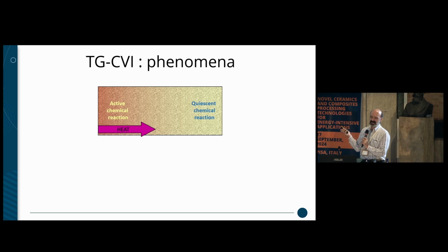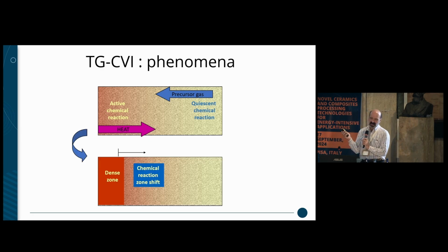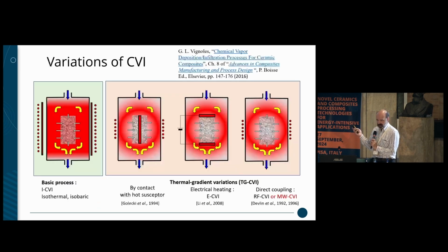And the idea is that, of course, the chemical reaction is active in the hot part. Then the precursor gas makes more or less the opposite way. And this results in a dense zone here, and you're shifting everything in the direction of more precursor gases entering the material. And variations of CVI, including thermal gradients, are numerous, and there's a long literature on that, dating back to the 80s or to the 90s.